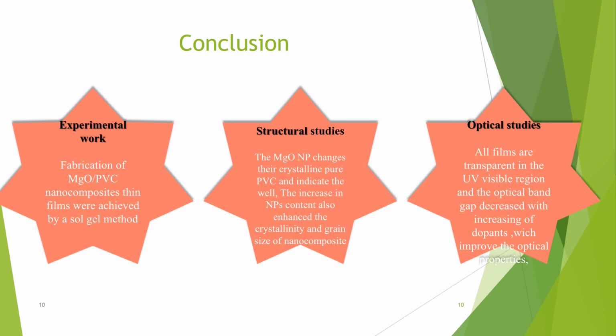The general conclusions are as follows. The experimental work revealed that fabrication of magnesium oxide PVC nanocomposite thin films was achieved by the sol-gel method. The structural studies confirmed that the magnesium oxide nanoparticles change the crystalline nature of pure PVC and indicate good dispersion of the nanoparticles in the matrix, and the increase in the nanoparticle content also enhanced the crystallinity and grain size of the nanocomposite.